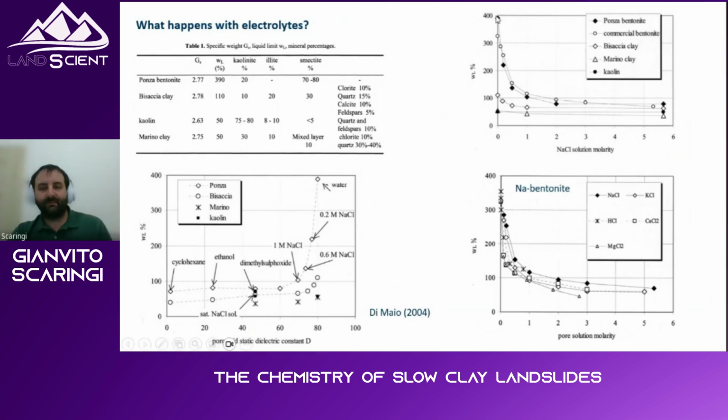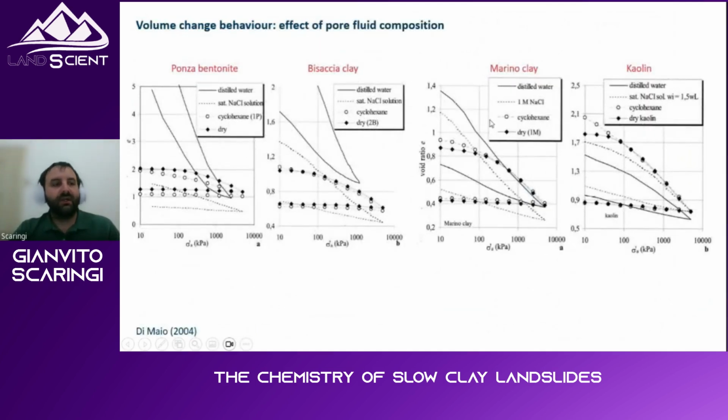If you prepare the same material with a concentrated salt solution, you will obtain much, much less liquid limit, and hence you will obtain less plasticity index, less activity even of the clay. Basically, the salt solution is inactivating the clay. It's making it stronger by inactivating it. So you see the big difference when you go from 0 to even small concentration and then larger concentration.